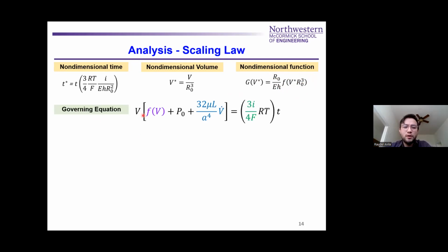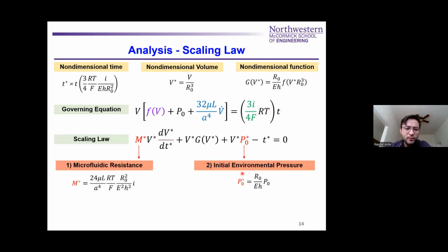So we go from having our governing equation, which looks like this, a first order ODE, to a scaling law that can be written in the following way. All the star parameters mean that this is a non-dimensional equation. And we can quickly identify two terms that are highlighted in red. One is the microfluidic resistance. This is a very important term, and it groups about 9 of those 12 terms that I mentioned previously. We have the influence of the microchannels, the length, viscosity, the temperature, two constants, then the radius of the membrane squared divided by the modulus squared, the thickness squared, and then the influence of the current.